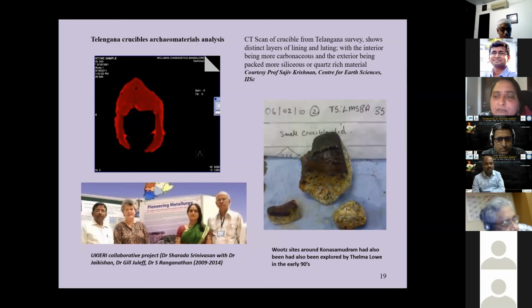And just to tell you also that when you talk of the chemistry, I'm now trying to concentrate on the crucible, which is more the chemistry than the metallurgy. So you find that the crucible as a refractory here has these two layers. There's the inner layer and the outer layer. And the inner layer is more carbon rich or carbonaceous, as you can see by the CT analysis.